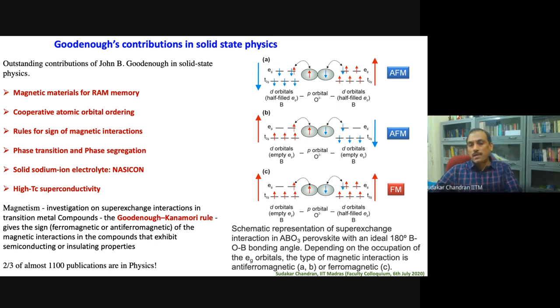The super exchange interaction between transition metal ions, for example, is antiferromagnetic when the virtual transfer between the overlapping orbitals takes place when the orbitals themselves are half filled. The particular case I have shown is for a 180 degree metal cation-oxygen-metal cation bonding angle. In fact, such a prediction works even for bond angles between 120 degrees and 180 degrees.